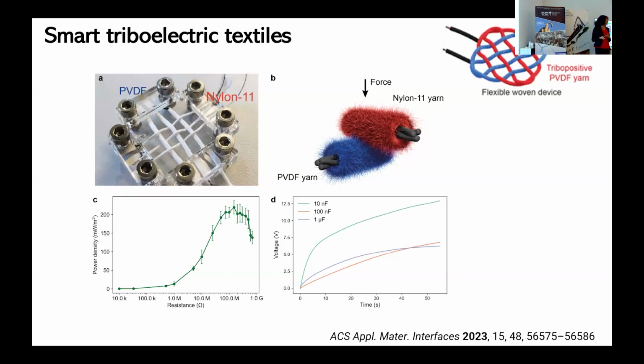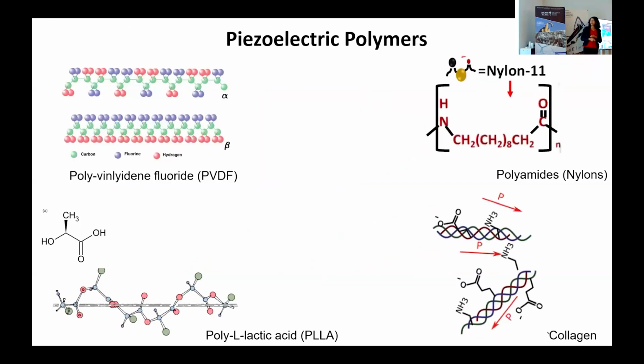We showed that it was washable. So apparently for something to qualify as a textile, you have to show that it is washable. So we stuck this into the washing machine a few times, and it works. So that's work we've done with nylon. I'll move on to the next one, which I want to talk about, which is poly-L-lactic acid, or PLLA.